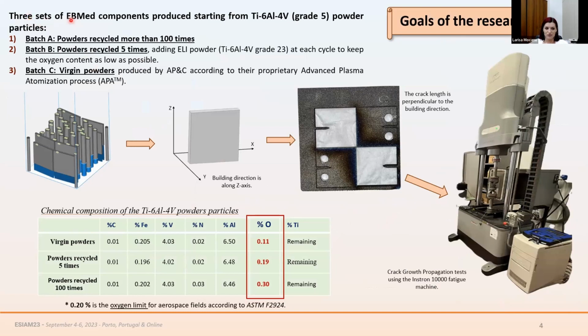we analyzed 3 sets of components produced with the electron beam melting. And these components were produced starting with 3 batches of titanium powder particles. The first one is the batch A, which is a powder recycled more than 100 times. Then we have the batch B, which is a powder recycled 5 times. And in this case, at each cycle, virgin powder was added in order to keep low the oxygen content. And then we have the batch C, which is the virgin powder produced by this company according to their advanced plasma atomization process. So for each of these batches, several different components were produced with the electron beam melting process.